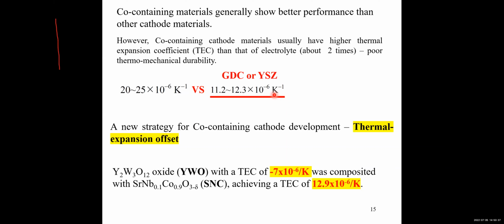This will decrease the fuel cell performance or even cause fuel cell failure. So it's very important to control the TEC of the cathode to ensure it's very close to the TEC of the electrolyte materials. In recent years, in collaboration with Professor Zongping Shao, we developed a new strategy for cobalt containing cathode materials using a thermal expansion offset approach.